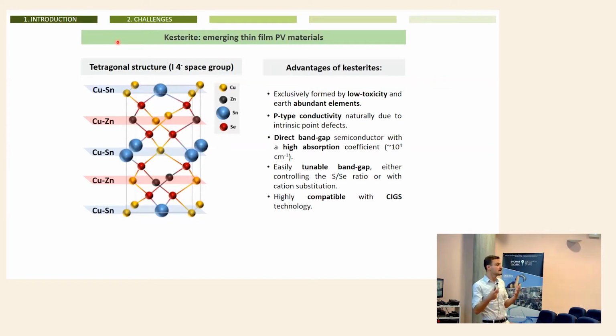Being very related with cadmium telluride, copper indium gallium selenide, and silicon from the structural point of view implies that we know many things about this material. And this material, for example, is fully compatible with any copper indium gallium diselenide production line. So a company producing copper indium gallium diselenide can very easily shift to kesterite or produce both together if necessary.